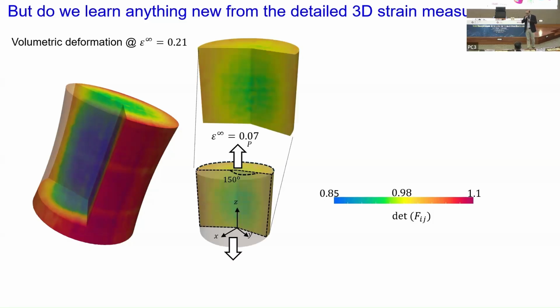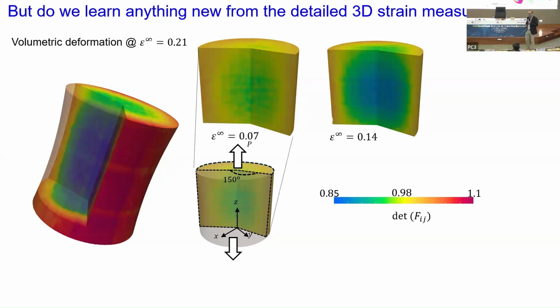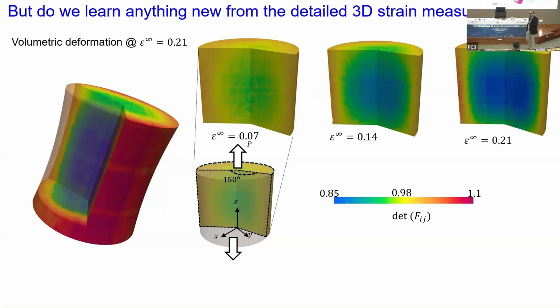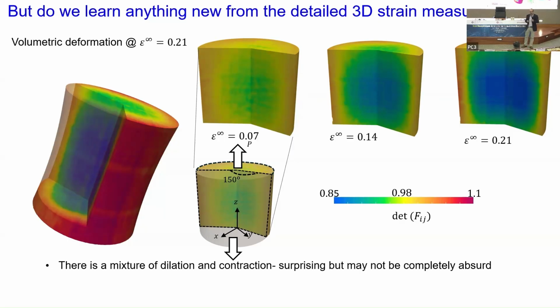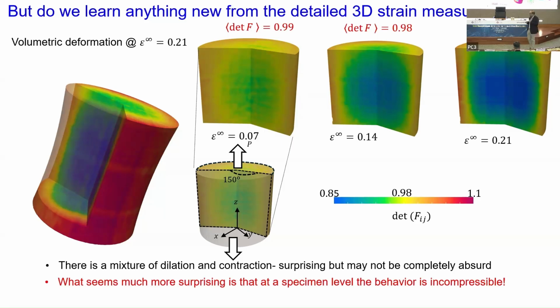Anyway, let's look at what happens over the course of deformation. This is 7% deformation, this is 14%, and this is 21% overall deformation. So this problem that we're getting seems to have evolved slowly as we increase the deformation. But as I said to you, everybody accepts that silicone rubber is an incompressible material. Well, is this totally absurd, that I'm getting this mixture? Well, let's look at what's happened here.